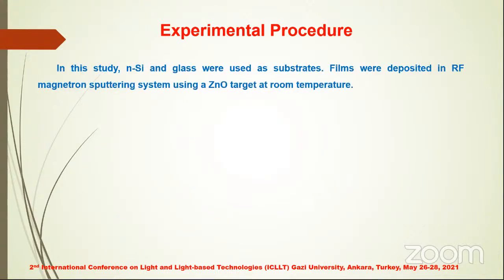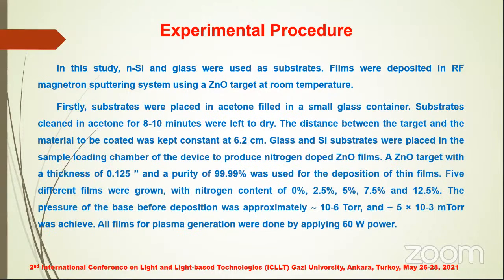Experimental procedure. In this study, n-type silicon and glass were used as substrates. Films were deposited in an RF magnetron sputtering system using a zinc oxide target at room temperature. Firstly, substrates were placed in acetone in a small glass container. Substrates cleaned in acetone for 8 to 10 minutes were left to dry. The distance between the target and the material to be coated was kept constant at 6.2 centimeters.